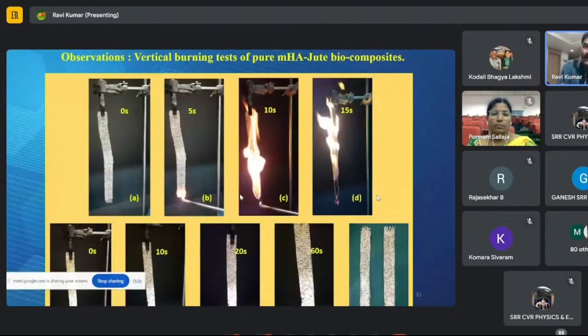Also, we tested the vertical burning test of the MHA jute biocomposite against pure jute. The pure jute burns continuously within 15 seconds. But in the case of the material deposited with MHA, even after 60 seconds the burning has not started. There is no catching fire on the surface. It means the MHA strongly resists heat waves on the surface, and the heat release rate is very low. As I explained in the introduction, we delayed the flame catch with the deposition of micro or nano layers on the surface of any material. It is only jute here. We also studied cotton and silk, but that will be explained in the future.